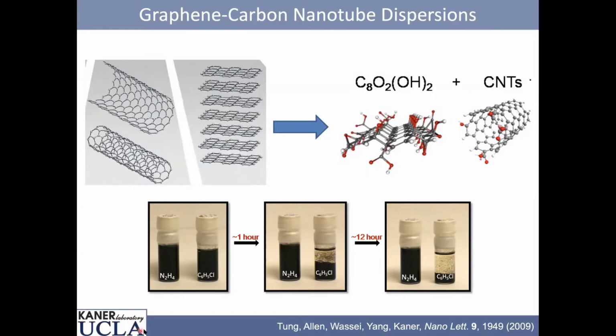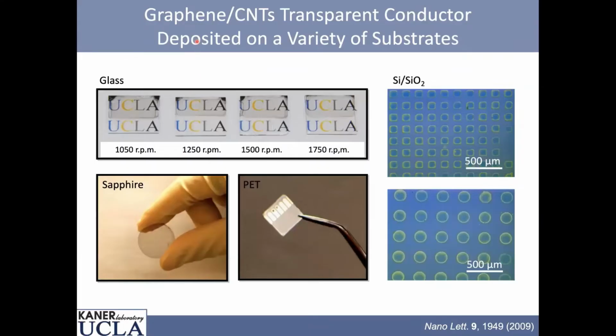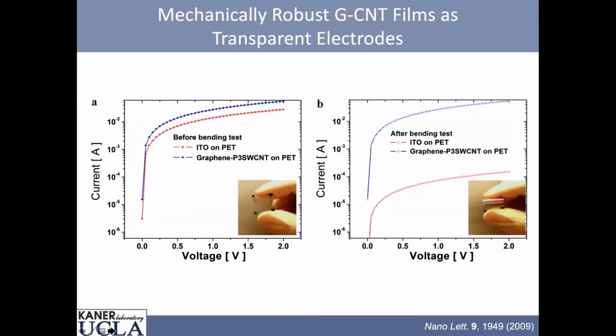So hydrazine is a really good dispersing agent for these. And once we disperse them, we can put them on any substrate you want. So here we spun them on glass, and you can see the faster you spin them, the thinner the layer of graphene and carbon nanotubes. Put them on sapphire, you can put them on plastic, you can put them on silicon. Okay, we're most interested in the plastic.